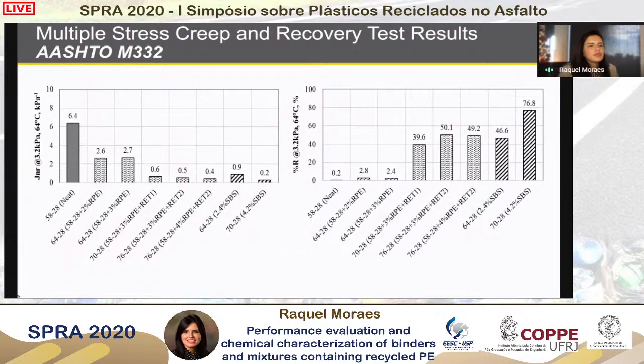So for performance comparison, 2 SBS modified binders, which had similar PG and delta Tc as the recycled polyethylene blends, were also used for comparison purposes. And we can see that both the 2% and the 3% recycled plastic modified binders had a very significantly lower JNR at 3.2 kilopascals and at 64 Celsius in comparison to the neat binder, which can be used as an indication of the effect of the recycled polyethylene on improving the rutting susceptibility in comparison to the base binder. Adding the recycled polyethylene and the terpolymer in combination improved this susceptibility even further.